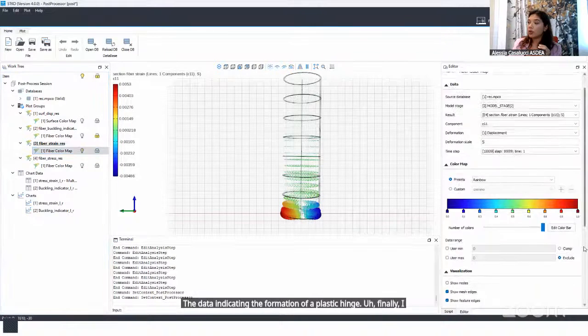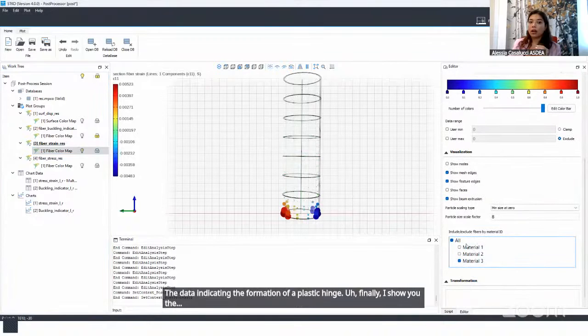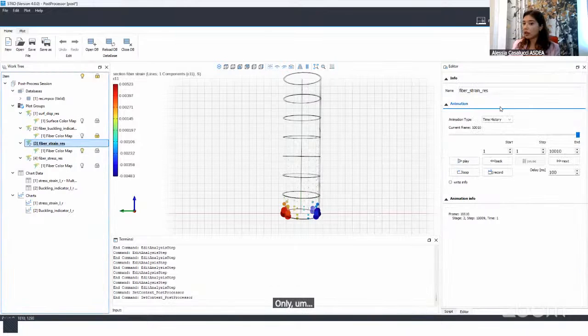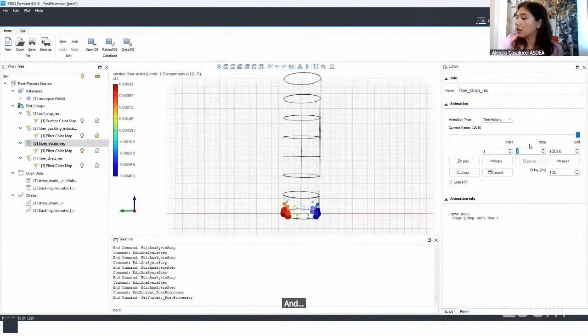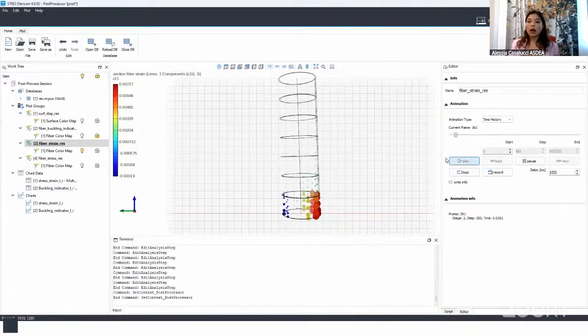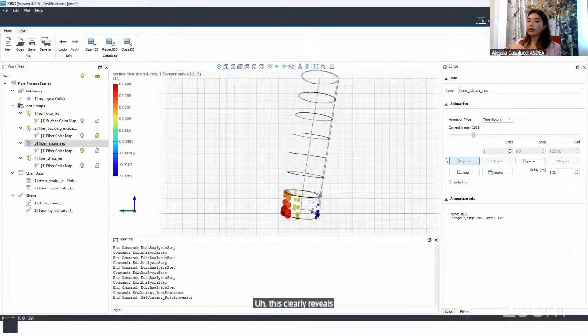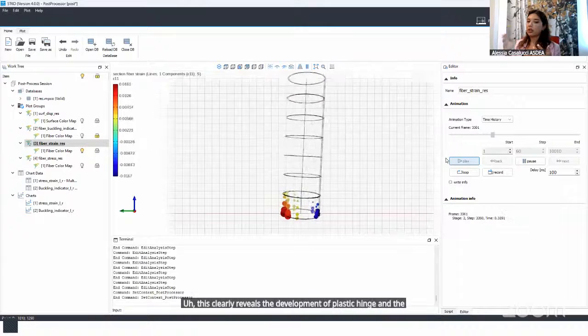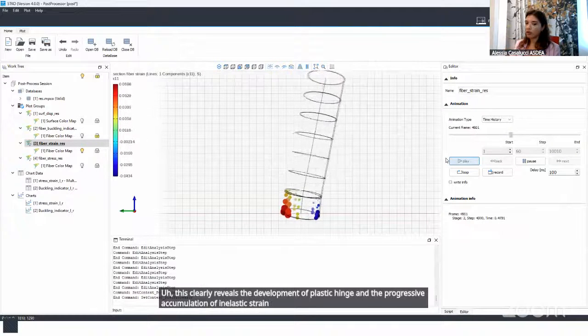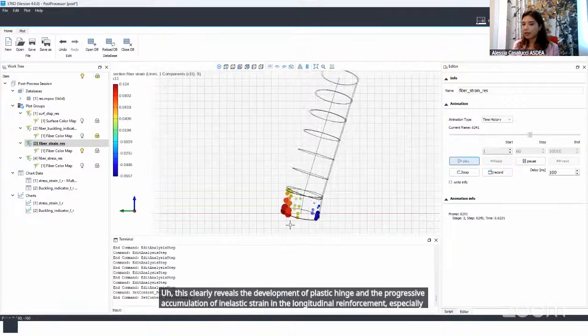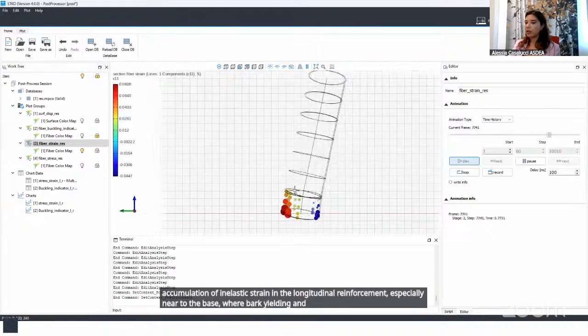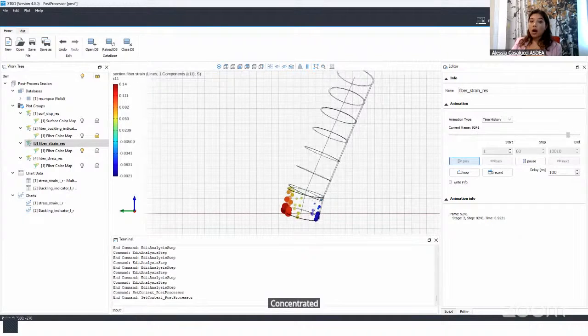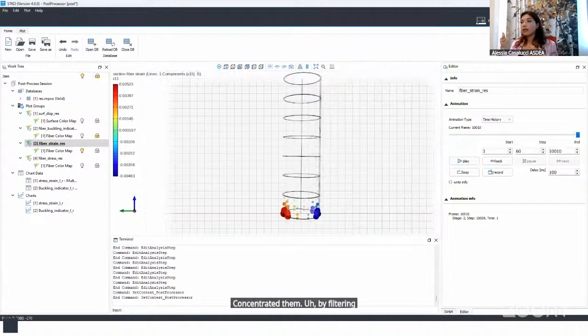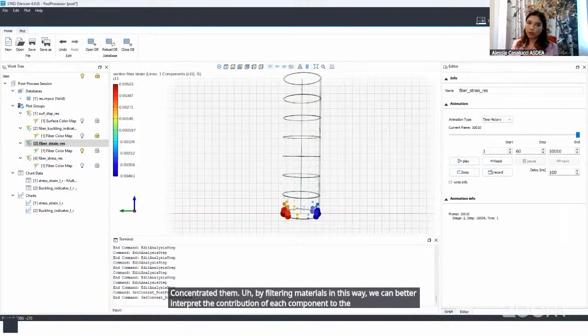Finally, I show you the strain distribution only in the steel fibers. This clearly reveals the development of the plastic hinge and the progressive accumulation of inelastic strain in the longitudinal reinforcement, especially near the base, where bar yielding and cyclic degradation are most concentrated. By filtering materials in this way, we can better interpret the contribution of each component to the section overall behavior.